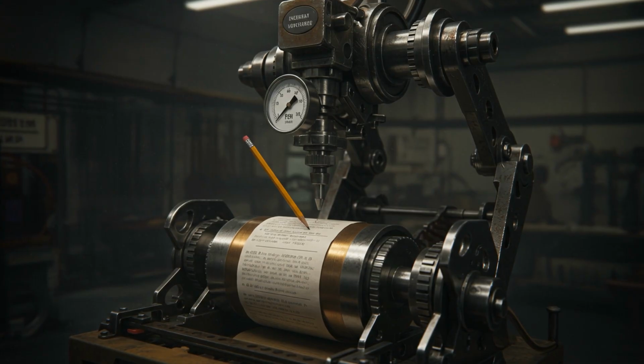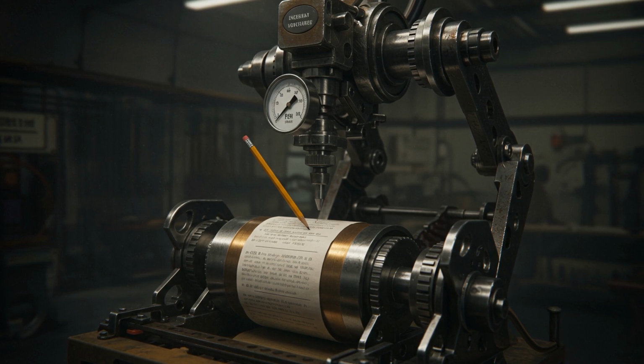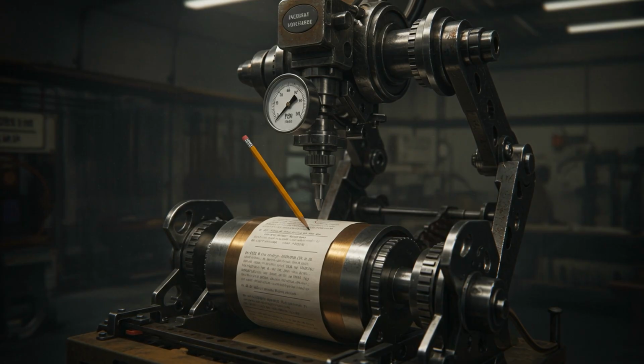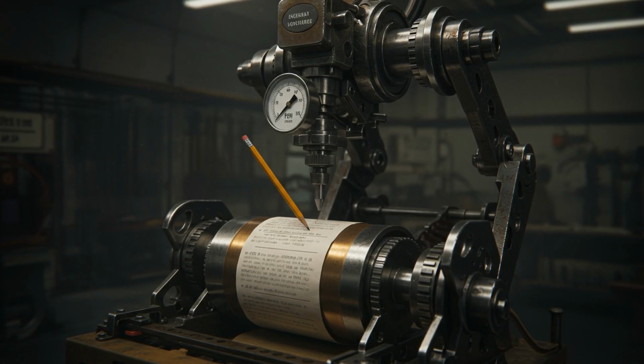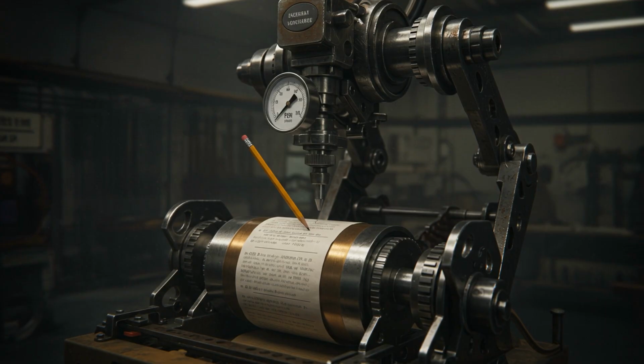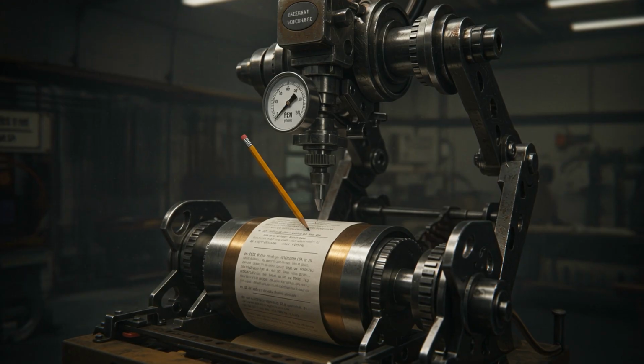A mechanical arm applies increasing pressure to the tip until it snaps, ensuring the lead meets the required break strength standards. Another machine performs a wear test, scribbling miles of lines to calculate how many feet of writing a single pencil can produce. On average, a standard HB pencil can draw a line 35 miles long. Engineers also check for light fastness and smudge resistance. Every batch is verified for lead centering and wood quality. Only after passing these rigorous stress tests are the pencils sharpened and packed.